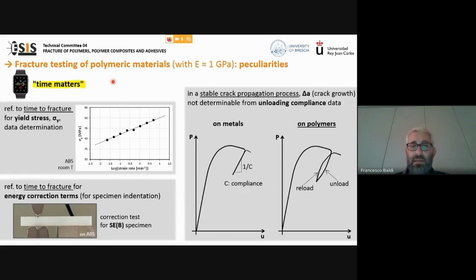experienced during the test. Therefore, I have to refer to the time to fracture in order to choose a value of yield stress determined with a time to yielding which is quite similar to the time to fracture. Similar consideration applies also when I have to perform energy correction tests, for example, for the specimen indentation, that is quite important when we deal with plastic polymers. I have to refer to the time to fracture in order to obtain energy data which might be used with data obtained in fracture tests.